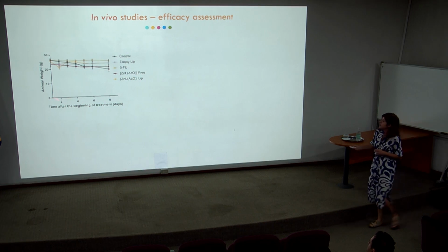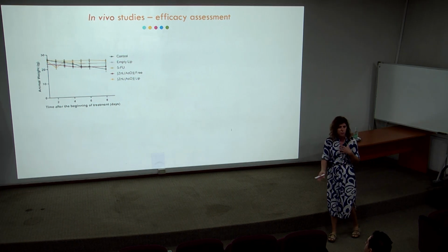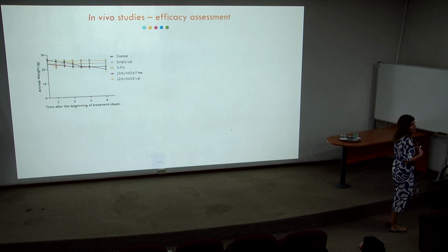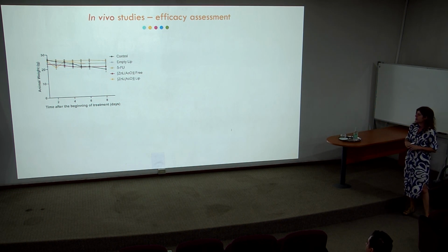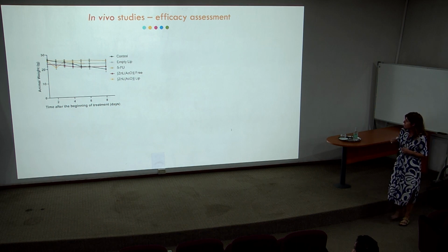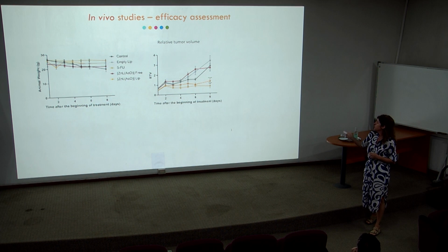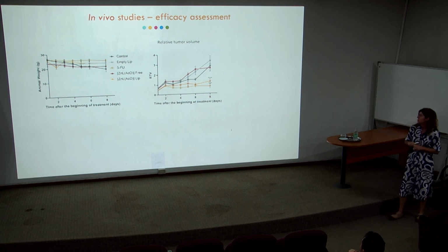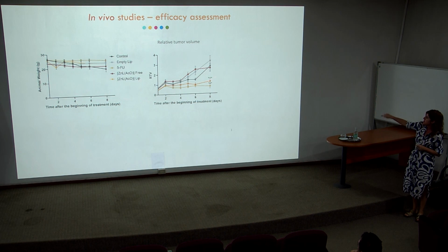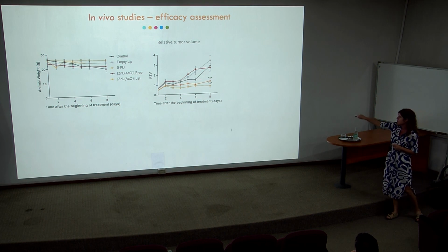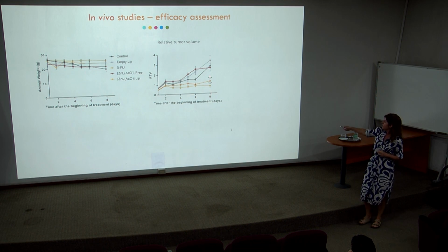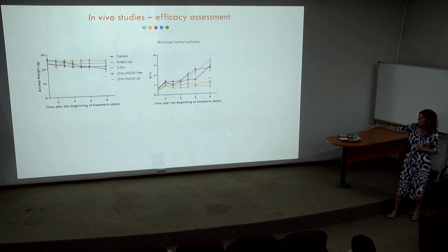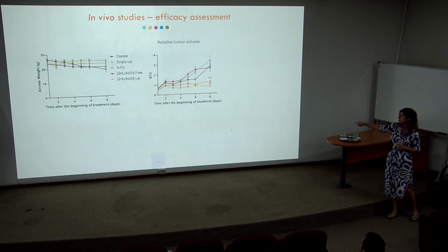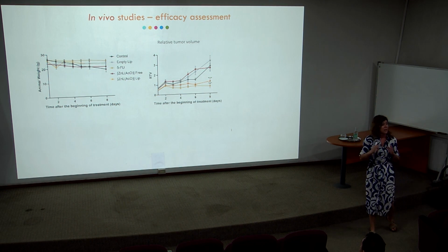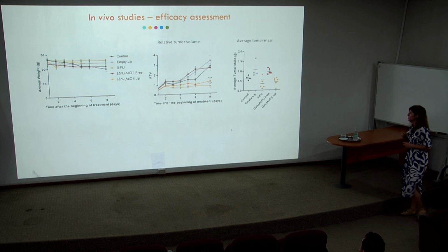Here I show you that, of course, the animals were controlled for pain, distress, etc. You can see that in all groups the animals' weight did not change much. In the end, we evaluated the relative tumor volume, and I think you can clearly see 2 groups here, this one on top and this one below. After 8 days of treatment, the liposomal formulation, which is this one, and no, this is 5-fluorouracil, this is the liposomal formulation of the complex, clearly reduced the tumor size, the relative tumor volume.